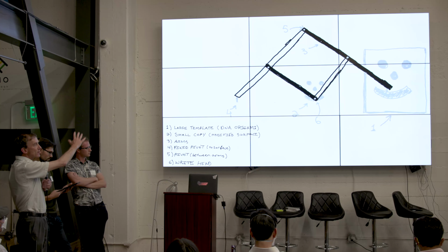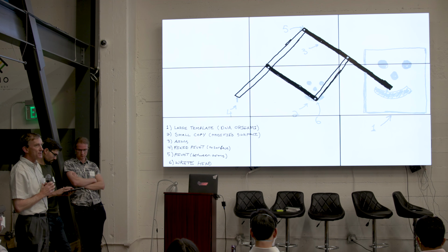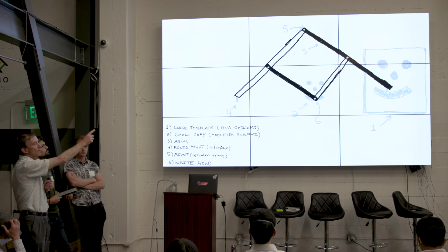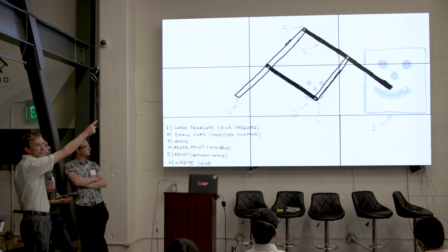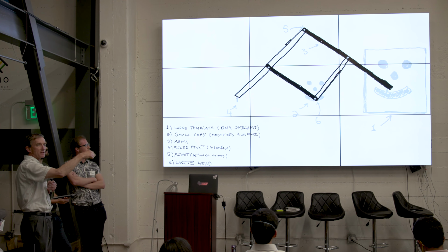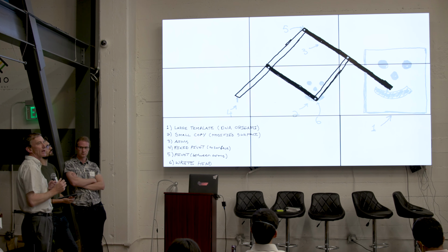So the difficult thing is making the pantograph, making the apparatus. It's not that impossible. Our idea is that you build the rods, the rods have to be rigid. The rods are gold nanorods, there might be carbon nanotubes, there might be semiconductor nanorods. These things are intrinsically rigid. We then have to make and position the hinge at the bottom, the hinges within the pantograph, the write head, the attachment of a DNA strand on the end of this thing, which allows us to position it. So the difficult bit is putting the functionalizations on these rigid structural elements.